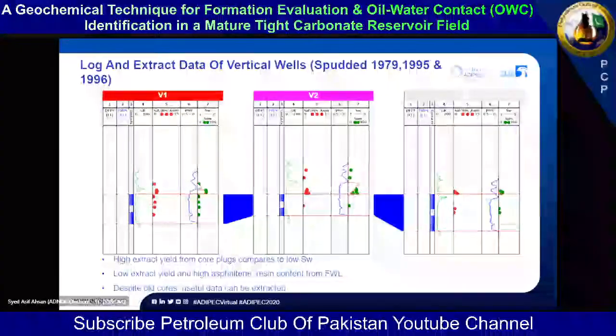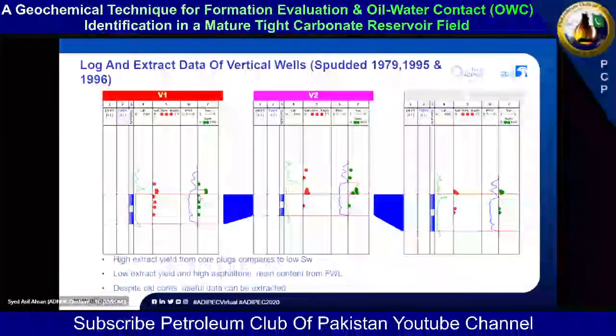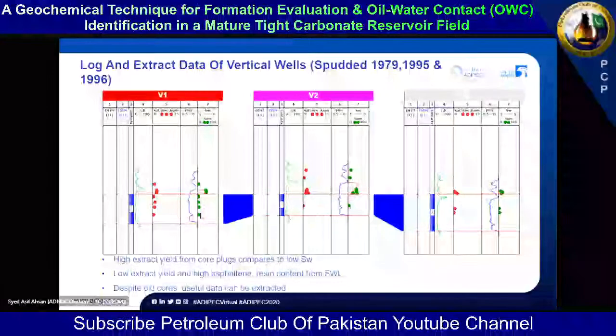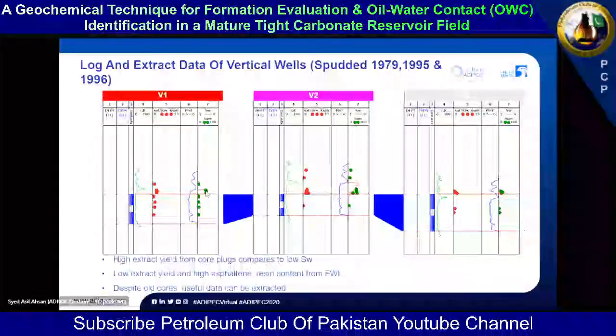So the dense layer is also showing the low extract yield, and all the core plug samples coming from the free water level are also showing the low extract yield, and the high extract yield is shown in the proper oil column, which is matching nicely with the water saturation derived from petrophysical means.